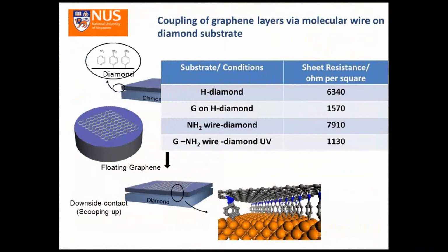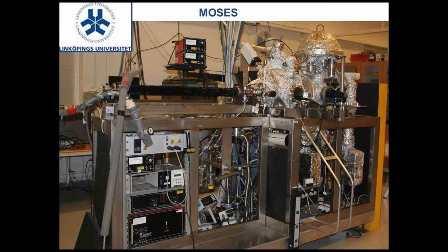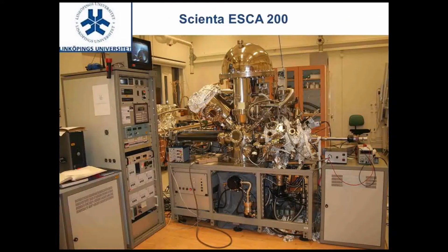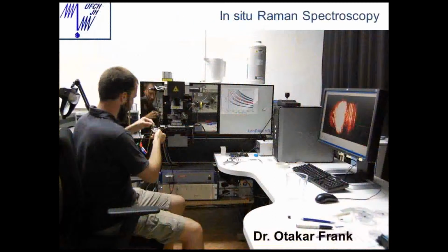Developed in collaboration between IMEC and NUS in Singapore, it was found that graphene coupled to diamond via a molecular wire gave more efficient charge collection to enable generation of higher photocurrent. The information related to interface properties between dye and substrate can be extracted from XPS and UPS. Also, other methods of characterization were used.